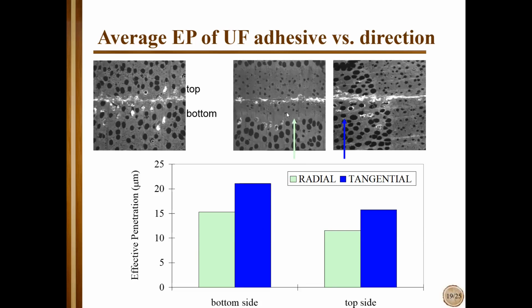The main inhibitor for adhesive penetration was late wood. So in this case, as you see in this photograph in the middle, adhesive actually concentrates only in the adhesive bond line. It cannot penetrate through this dense, less porous late wood. You see here some adhesive, but this came along the lumen of wood cells. Wood was probably cut at a certain angle, and so this adhesive here came from the bond line, let's say a few millimeters below.